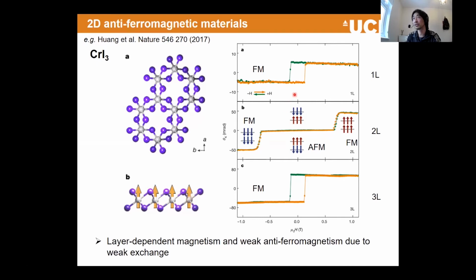This is the schematic of it. You can see that up to about less than 1 Tesla, these two layers are polarized up and down. These are the two different states. Then when you apply a large enough field in the perpendicular direction, you flip one of the spins into the same direction so that it tends to become a ferromagnetic phase.